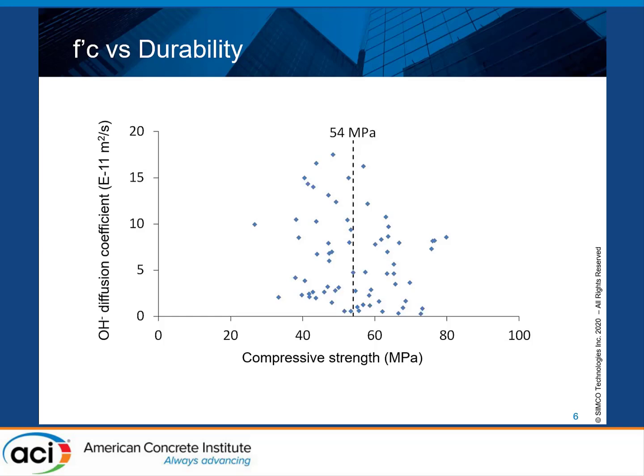So for a mix with 54 MPa, for example, which is the average we get from those results, the diffusion coefficient may range from nearly 0 to, well, don't pay attention to the type of diffusion coefficient here because it's the one we use as an input in our model, but you can see clearly there's a large scatter in the diffusion properties for mixes that have comparable compressive strengths. And most of these compressive strengths are above 40 MPa, so which would be